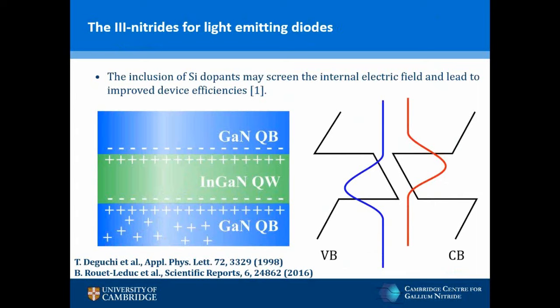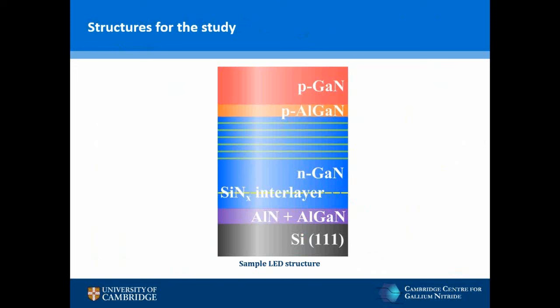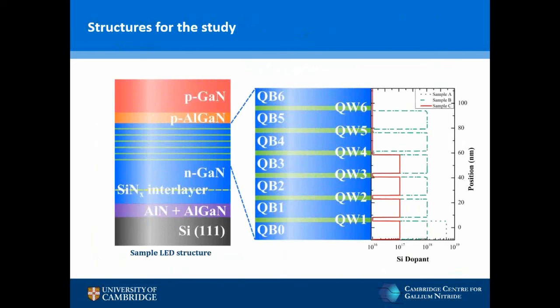In collaboration with our industrial partners Plessey Semiconductors, we developed a range of samples to investigate and optimise the effects of silicon doping. The overall structure consists of an aluminium nitride buffer layer grown on silicon, followed by graded AlGaN for stress management, an N-type region with a silicon nitride interlayer to reduce dislocation density, six InGaN quantum wells with gallium nitride barriers, and a magnesium-doped gallium nitride P-type cap. The first sample, referred to as sample A, was grown with silicon doping of 1×10¹⁸ per cm³ throughout, including a higher doped region of 5×10¹⁸ per cm³ below the first quantum well.